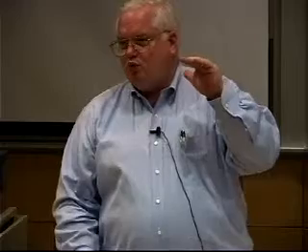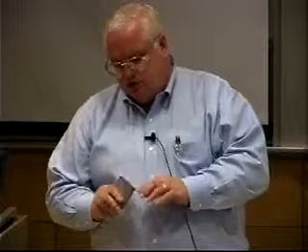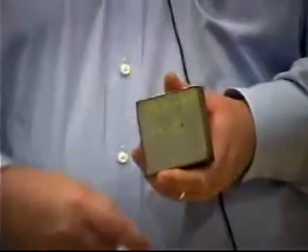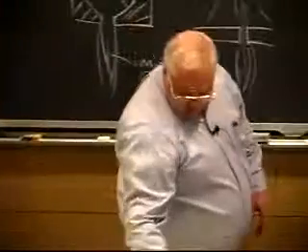You can't cut 24-inch thick like you can with oxyacetylene, where you're burning through the material and using the material itself as its own ignition source. Here you're just melting through. Now this is just a simple square, and you'll notice where they start and where they turn corners, they don't get nice square corners. That's because I have a thermal pattern that I'm carrying along, and when I turn the corner I lose the symmetry of that thermal pattern, and that creates some bad corners, which is still a problem for plasma cutting. That's in stainless steel.